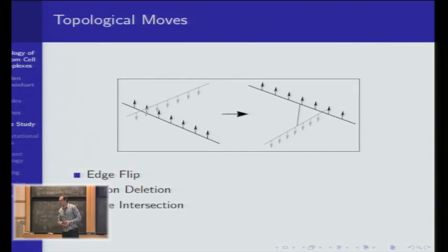And as Menachem pointed out, since we are in 3 dimensions, we sometimes have this case where 2 unrelated edges are going to intersect like this. Now, I tried two different topological moves when this occurs. One is you can just ignore it, and then you can run much larger systems. And the other is when you have 2 edges that meet like this, you add a 3rd edge between them. You form a new edge. And it turns out that using the method of swatches, you can show that for the long-term steady state, the choice of topological move here does not matter. You get the same steady state. And I'll explain that more later.